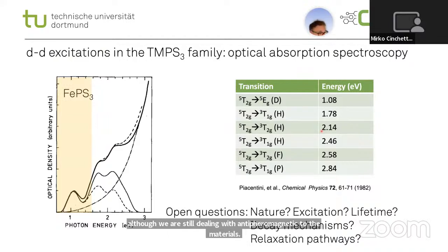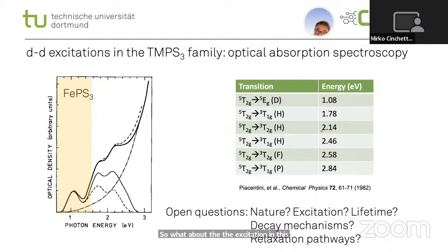So what about the dd excitations in these materials? These excitations were studied already in the 80s using optical absorption spectroscopy, but not in the context of magnetism. So the figure here shows the optical absorption spectrum of iron PS3. You see here at a photon energy of around 1.5 electron volts, we have the onset of the band gap. But even below the band gap, we have this peak, which can be fitted, and this peak corresponds basically to the lowest energy dd transition in this material. So this is a transition which happens below the band gap energy of the material.